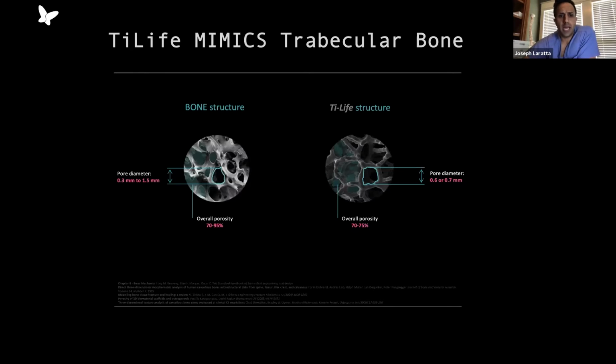And when we look at the structure of trabecular bone, we can see that the pore diameter is usually somewhere around 400 to 600 micrometers, and the porosity is about 80%. And when they designed the TiLife structure, they tried to design it similarly. So pore diameter, again, 600 to 700 microns, and overall porosity around 75%.